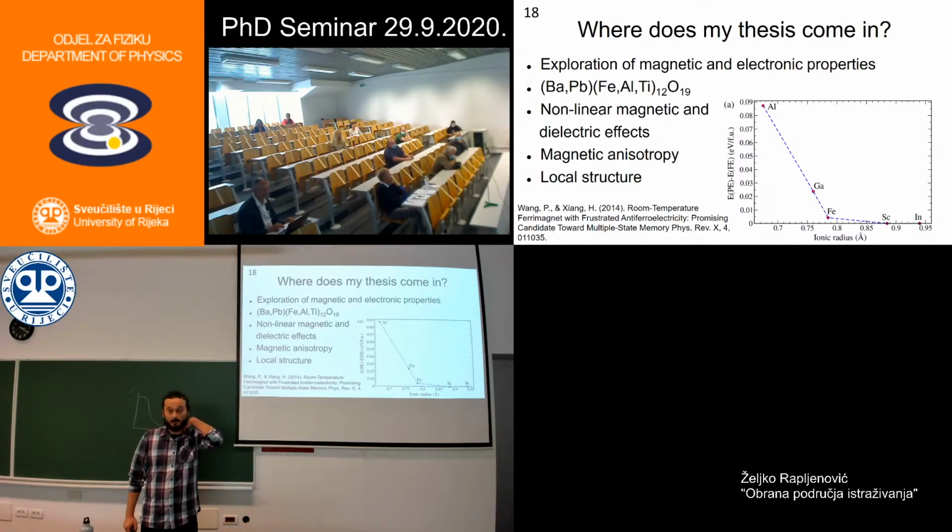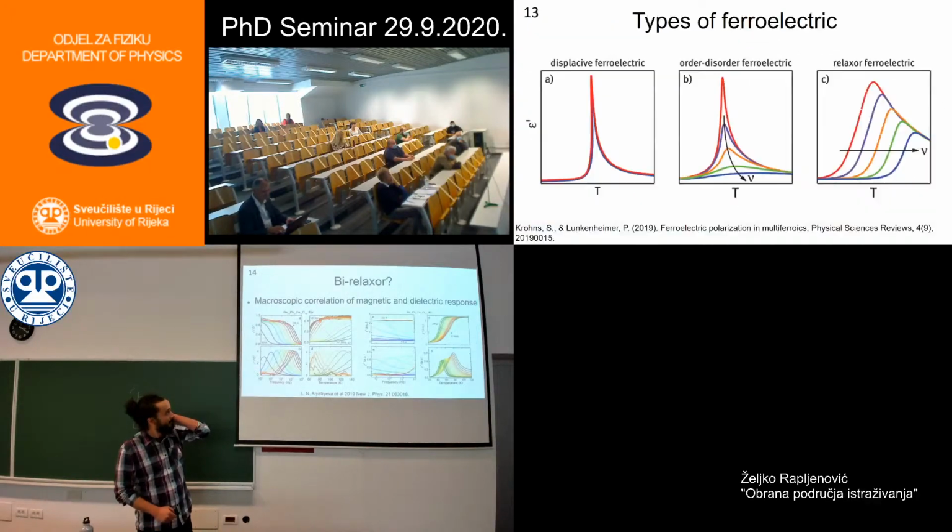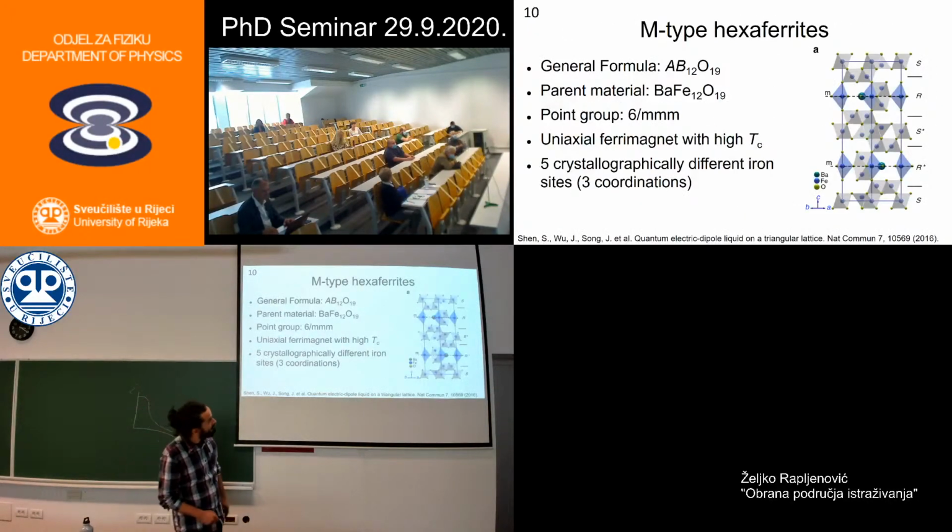Well, I'm not sure about the tetrahedral site or the octahedral sites for the Jahn-Teller effect. Maybe I could see it from the structure. Does this octahedron seem distorted? Somewhat, yes, it seems distorted. Usually you then break symmetry with the distortion, so the ion goes from the central symmetry position to the left or right of the oxygen position. I was just curious, since nobody is saying anything about Jahn-Teller in this material. Not that I know of.